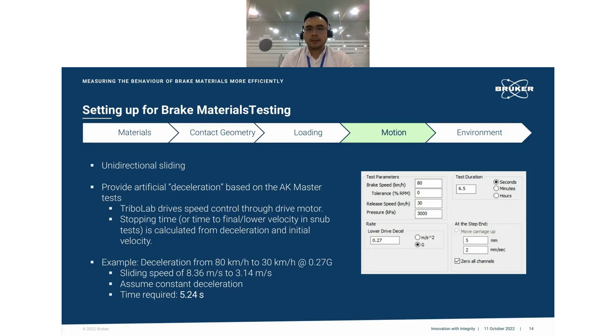So for example, over here, as you can see on the right on the screen, first the motor will be driven up to 80 kilometers per hour, and then the loading will happen. The brake pad will be applied to the rotor disc at a contact pressure of 3 megapascal, and the motor will slowly decelerate down to 30 kilometers per hour. During this duration, the torque value and the coefficient of friction as a result of this deceleration would be collected and presented. An example calculation based on a 0.27 g basic passenger car is established for this particular test. But throughout the entire AK Master test, there are a variety of test conditions that we will simulate.